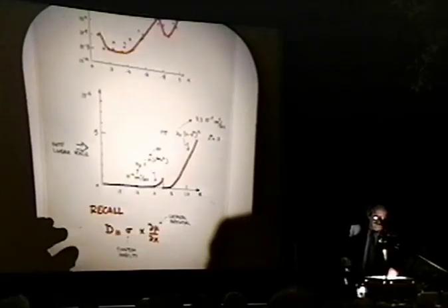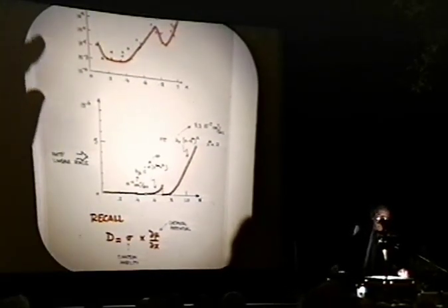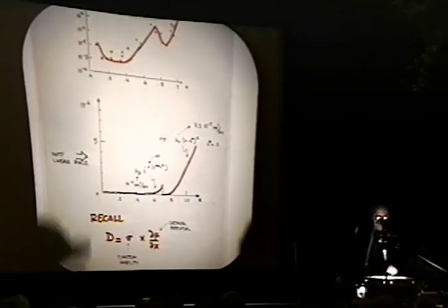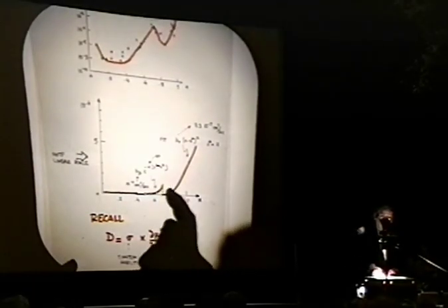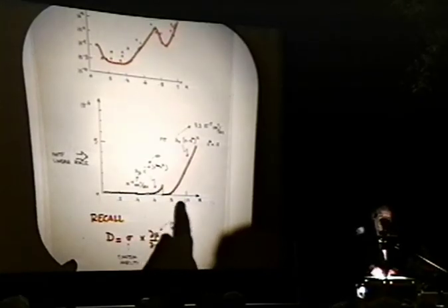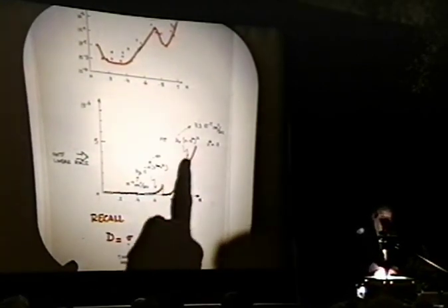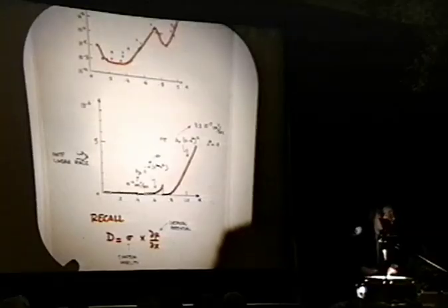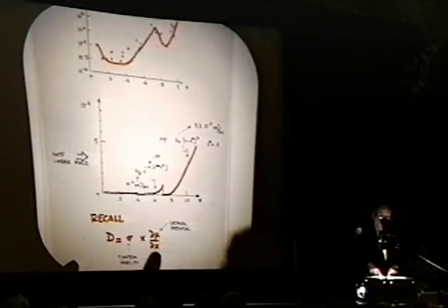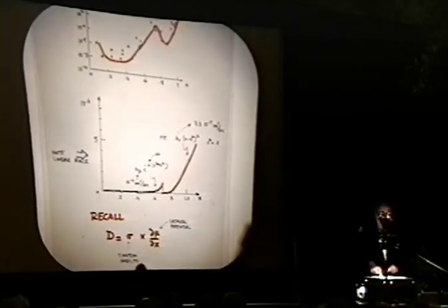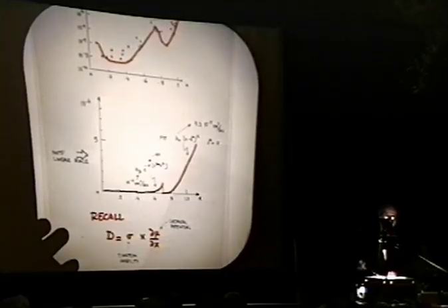And then you see essentially that if you put the diffusion coefficient in a linear scale, you can represent it this way, and there is certainly a discontinuity in this concept, where you have a very large diffusion coefficient, which goes all the way up to 10 to the minus 5 centimeters squared per second. And I recall here the diffusion coefficient is related to the Einstein mobility and the derivative of the chemical potential here, which of course shows that the very large derivative is reflected. So good, you see the behavior of this experiment.